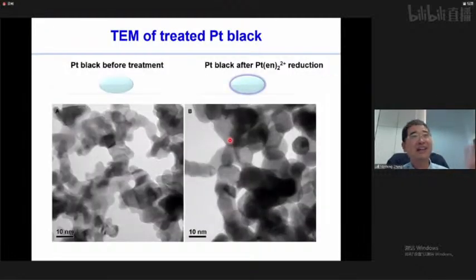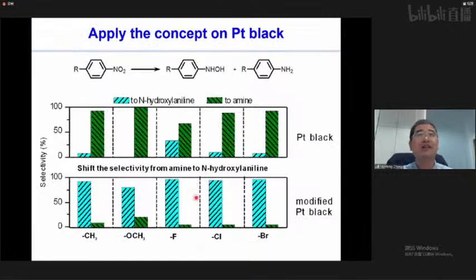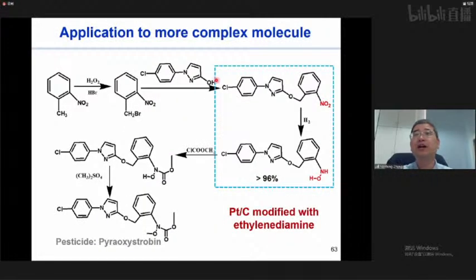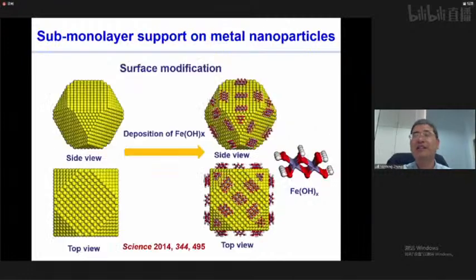So that's why the nanowire shape is not important. The ethylenediamine is so important. So that's why we can use palladium black, platinum black, and then modify it with ethylenediamine. Then we can switch their selectivity. So this concept actually has already been used for many important intermediates production in industries, like these pesticide intermediates, and it turns out it's quite effective.